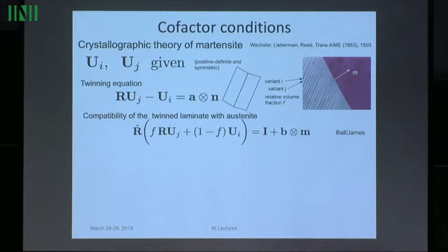So are there any additional hidden accidents in the lattice parameters that could make these two phases more compatible and therefore even further reduce the hysteresis, maybe improve the reversibility? And there are. So it's a matter, from a mathematical viewpoint, of looking for degeneracies in equations.